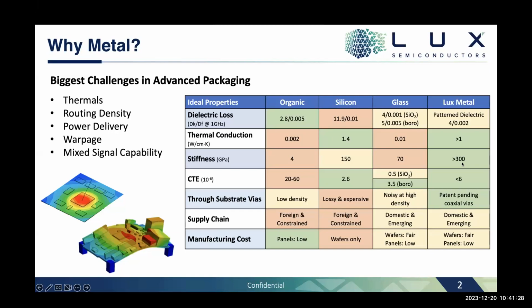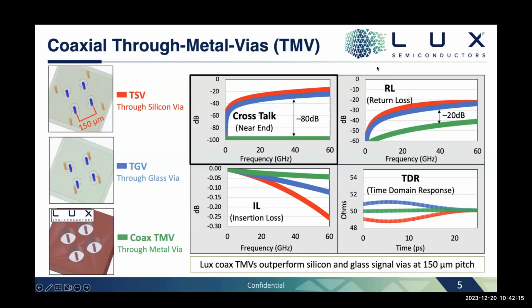To JP's question about the size of the package, we see that as well. The trend is increasing package size, and that places a lot of stress at the bumps on the periphery of the package. And this material is significantly more stiff than organic substrates, and so much more resilient to warpage as a function of temperature or stress. But I would say that the biggest thing our customers have been interested in are the through substrate vias, and so this is the last slide I have.